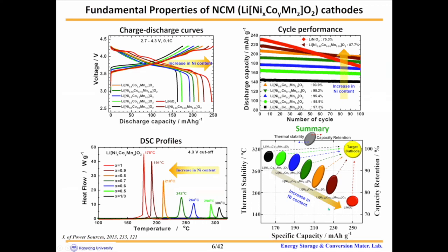However, based on this result, we believe that it is impossible to develop an ideal cathode with both high capacity and high safety just by changing the compositions. However, we need a cathode material with high capacity, good thermal stability, and outstanding capacity retention. In order to develop the target cathode, we should know the capacity fading mechanism for the nickel-rich NCM and NCA cathode materials.